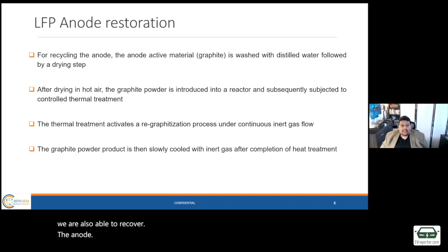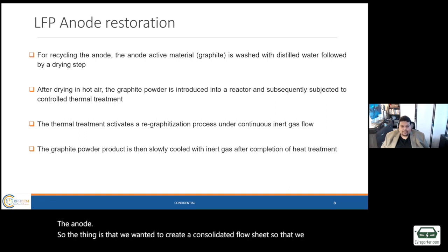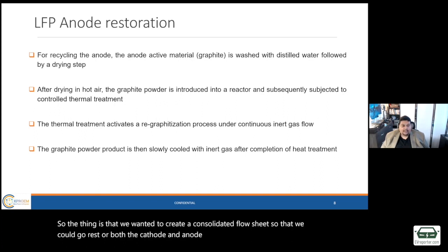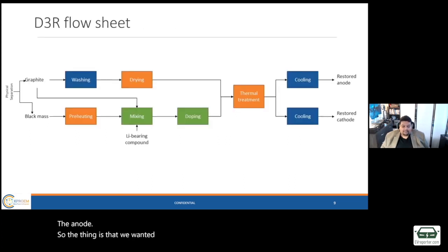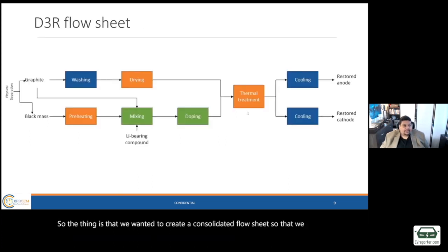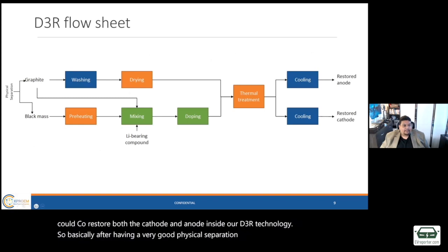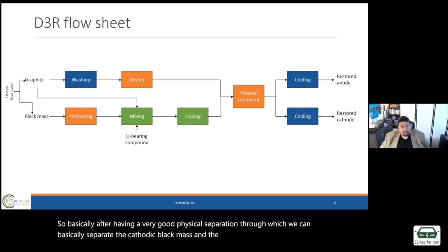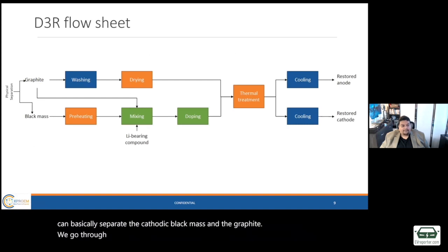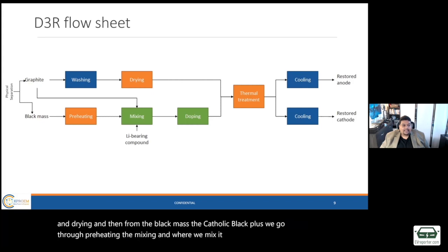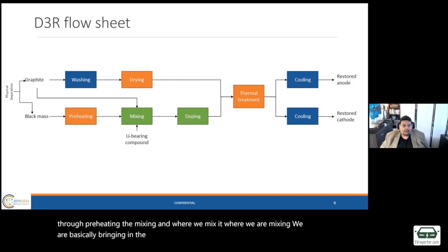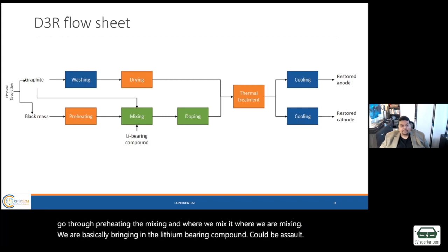So the thing is that we wanted to create a consolidated flow sheet so that we could co-restore both the cathode and the anode inside our D3R technology. Basically, after having a very good physical separation through which we can separate the cathodic black mass and the graphite, we go through a couple of phases. For the graphite, we go through washing and drying. And for the cathodic black mass, we go through preheating, then mixing, where we are bringing in the lithium-bearing compound, which could be a salt. And then of course, going through some doping.